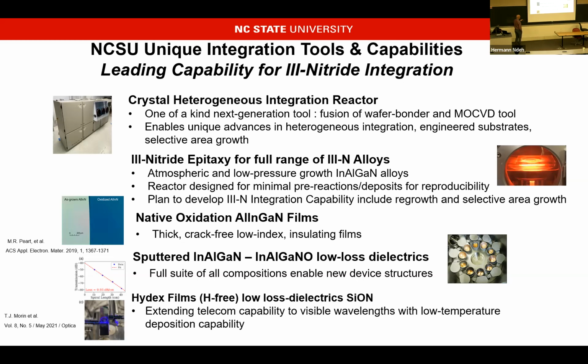And then we're also in the process of standing up these Hydex films. Infinera has been kind enough to allow us to take some of the recipes that we had for that, and we're going to stand that up in the NNF. What's very interesting about this is there have just been some recent reports. This is work that extended into the infrared. There have not been a lot of studies or reports of silicon nitride in the visible, but this is not Hydex; this is silicon nitride that shows basically a dB per centimeter in the blue. But again, this is a silicon nitride that people have annealed at 900 degrees C plus for many hours, right? So our hope is that we're going to be able to take this Hydex film and have low loss dielectric waveguides in the visible that we can integrate into our device.